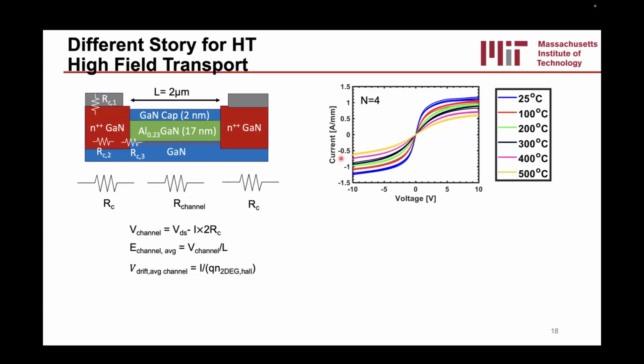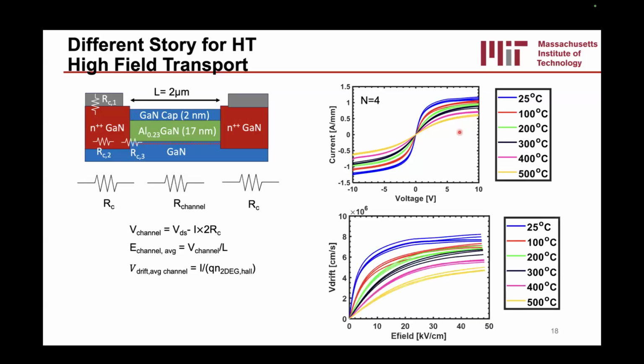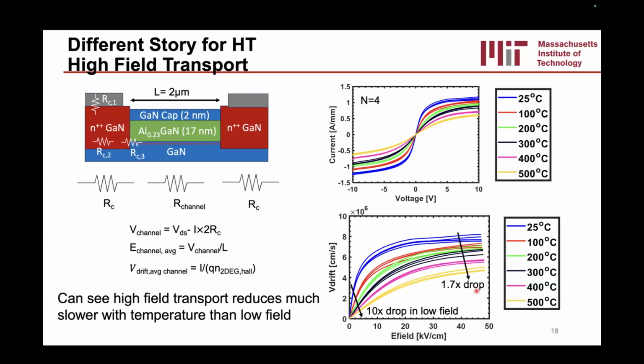Using these formulas, we can convert standard current-voltage measurements of this TLM structure from 25C to 500C, and convert them to basically drift velocity versus electric field measurements, which are a little bit more physically insightful. And from here, you can actually see two interesting things. One is that indeed in the low field limit, where the mobility is the main parameter, there is a 10x drop in the drift velocity. However, in the high field limit, the drift velocity doesn't change too much, about a 1.7x drop from 25C to 500 Celsius. And so we can see that the high field transport reduces much slower with temperature than the low field transport does. And so that gives us some idea of how we want to design our devices in general.